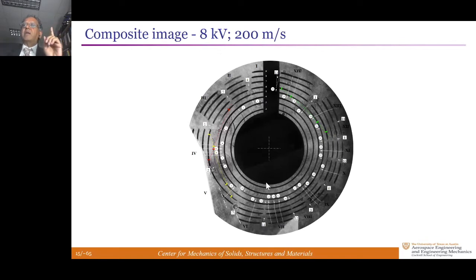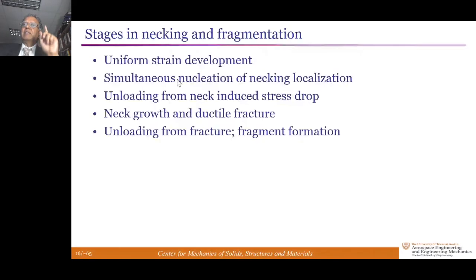We had done on the order of 100 experiments of that ring expansion test in different materials to collect overall information about the response. And the order or sequence of events is very clear from this set of experiments. First, there's uniform expansion of the ring, just one-dimensional stress state, very easy to calculate the response. Then there's the nearly simultaneous nucleation of necking localization at multiple locations. If the experiment had been done quasi-statically, the first neck that forms would unload everything else and there would be no further necking.